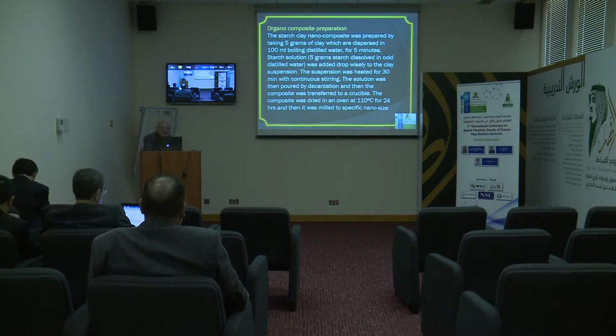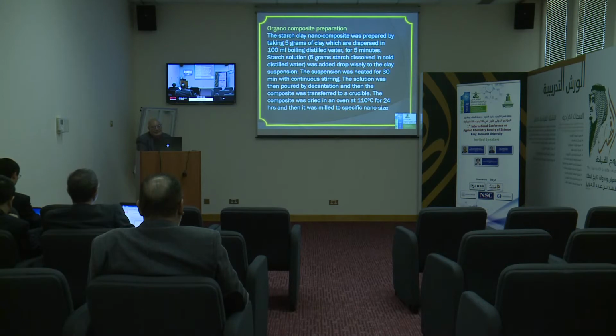The organocomposite preparation, starch clay nanocomposite, was prepared taking 5 grams of the clay, which are dispersed in 100 milliliter boiling distilled water for 5 minutes. The starch solution, which is 5 grams starch dissolved in cold distilled water, was added dropwise to the clay suspension. The suspension was heated for 30 minutes with continuous stirring. The solution was then poured by decantation, and then the composite was transferred to crucible. The composite was dried in an oven at 110 centigrade for 24 hours, and then it was milled to the specific nano size.